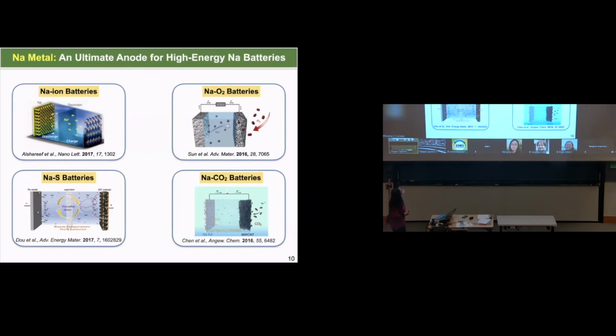If we look at all these sodium-based battery systems, one common thing for all of them is the anode material. Okay, they all use a sodium metal anode, especially these 3 high energy density battery systems. For the conventional sodium-ion battery, you can also replace the current anode material with sodium metal. In this case, you can further boost the energy density of the conventional sodium-ion battery system. So that's why sodium metal is considered, we call it, the holy grail of the sodium battery system, because it provides what we call the ultimate anode choice for the high